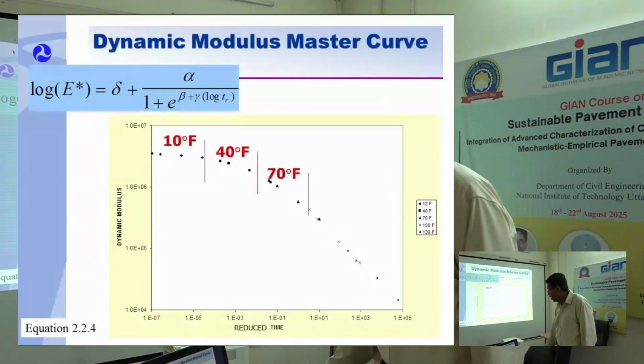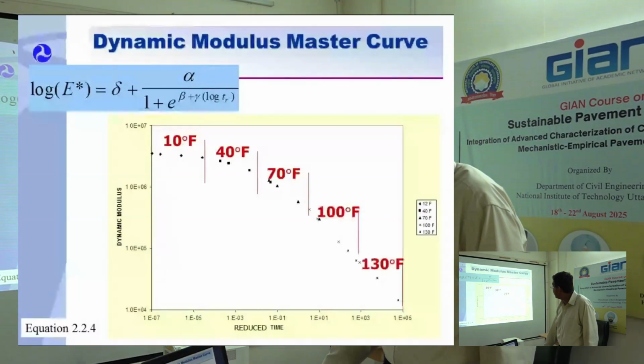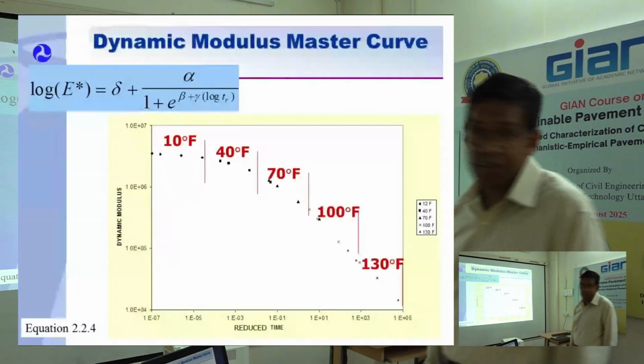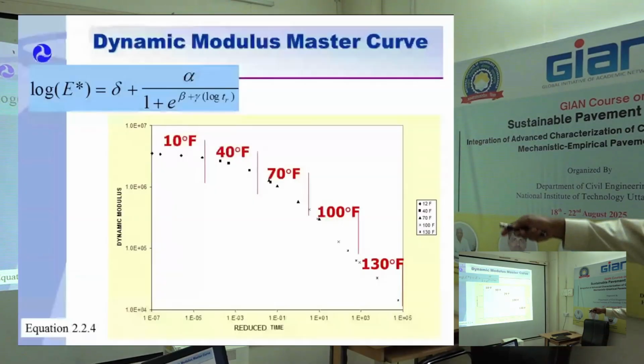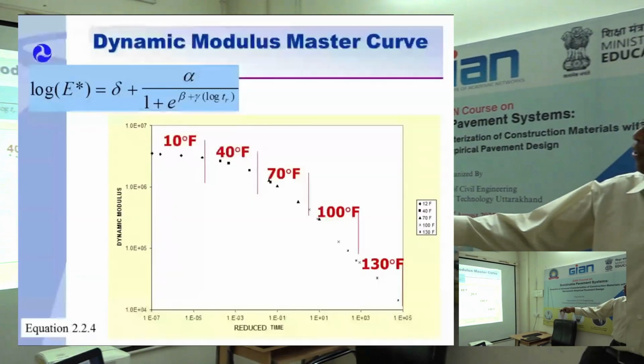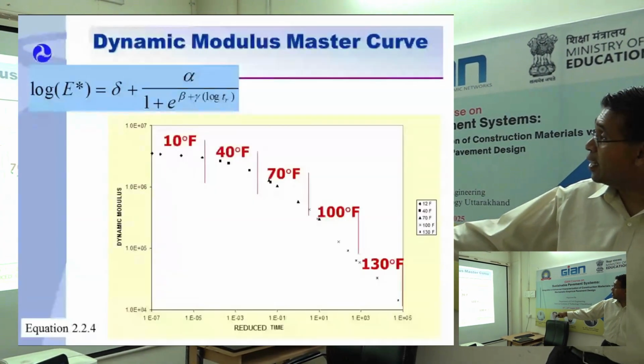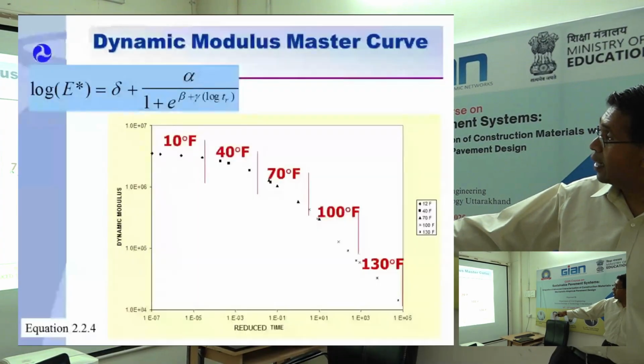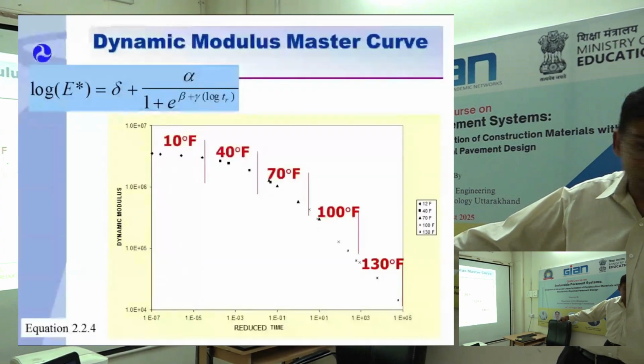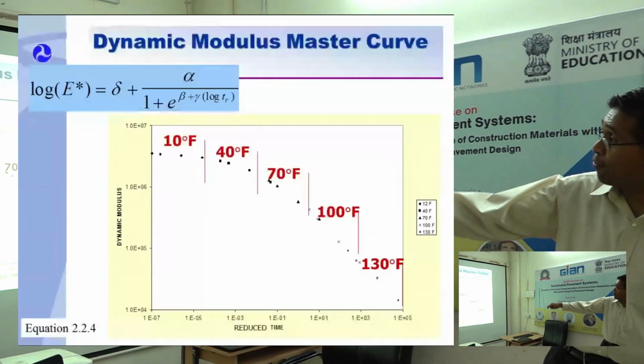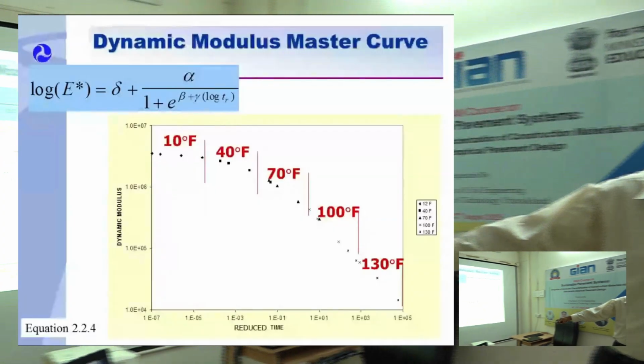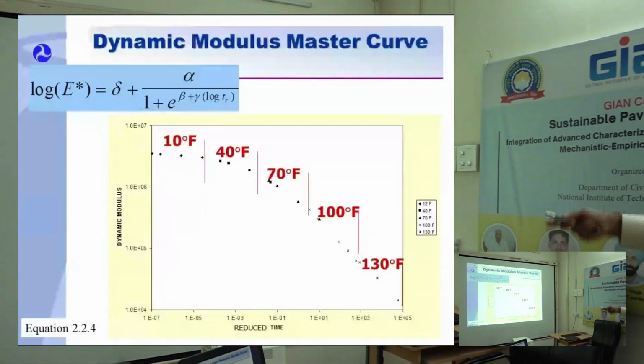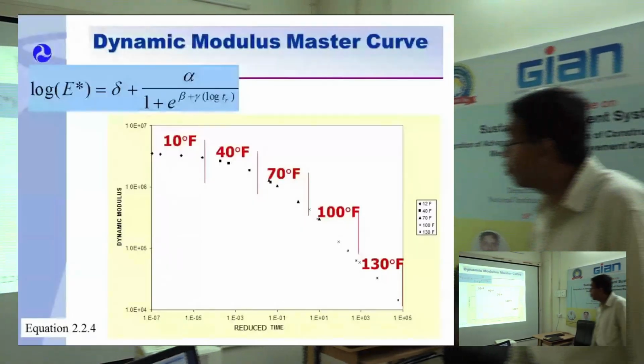10 Fahrenheit, 40 Fahrenheit, 70 Fahrenheit, 100 Fahrenheit, 130. So very well explained here. This is cold temperature data, 40 Fahrenheit, 70, 100. So you can see it by heat. Testing at 130 Fahrenheit, I'm getting data at almost 10,000 seconds. And at 10 Fahrenheit, I'm getting almost 10 raised to minus 7 seconds. Right? Beauty of testing different temperatures, I'm getting the same information.